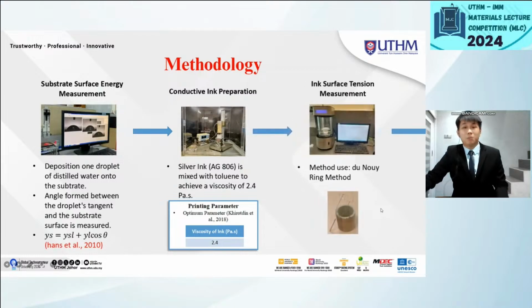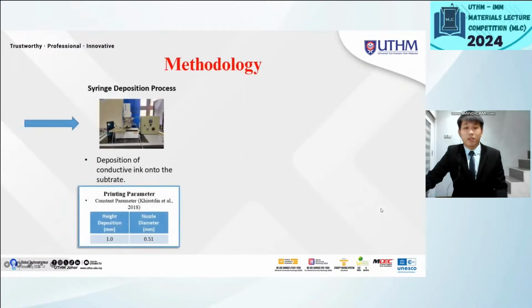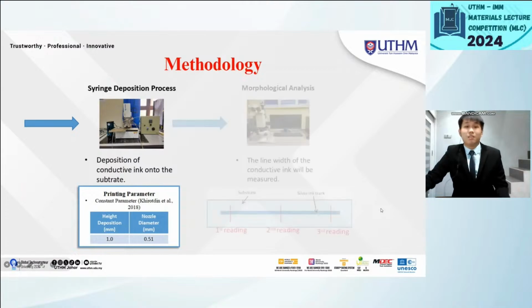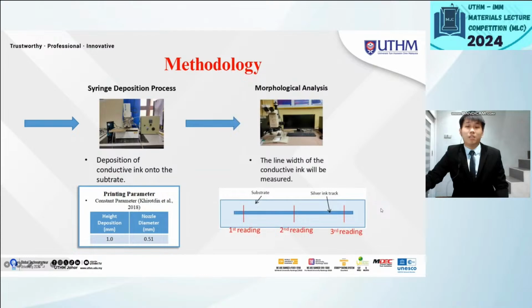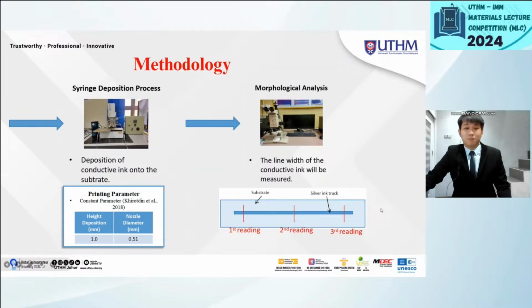Once the silver ink preparation is complete, the syringe deposition process will be carried out. The inks will be deposited according to the parameters determined by simulations. After the lines are deposited and fully cured, the line width of the conductive inks will undergo morphological analysis using an optical microscope. The percentage error will then be calculated to assess the accuracy of the depositions.